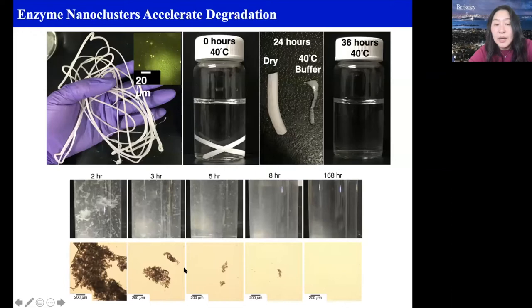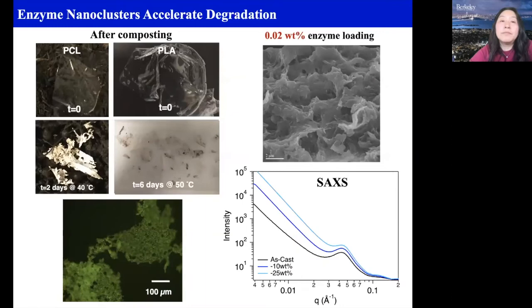So it really starts to degrade from the inside out rather than from external surface erosion. And then also the microplastics started getting smaller and smaller. So we have to extend this to see if it can go beyond just a test tube inside of plastic, because when you degrade it, you eventually are going to release the enzyme. So you have multiple processes going on. You don't want that to mislead what happened to the material under the composting condition. So this is exactly what we did.